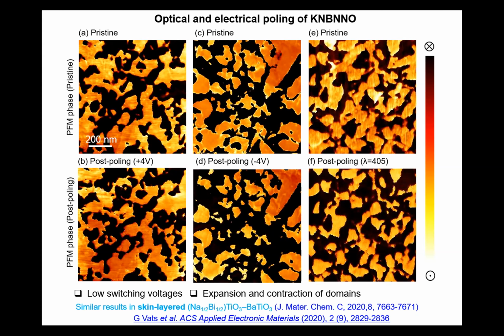Okay, another question is about this poling with full voltage. Is that DC poling or AC, where you apply a higher AC voltage? This 4 volts was DC. So you measure the domain structure and then use DC to pole it. While poling, do you apply the AC voltage to scan the image? No. I acquired this image, then I did another scan where I just applied +4. After that, I removed +4 and did this normal PFM scan. So there is no influence of the AC signal on these results. Okay.